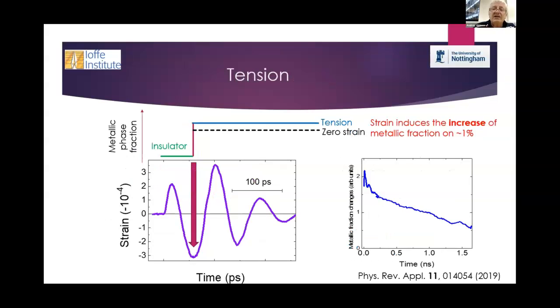So I will show the results first: what happens with tension when we excite the phase transition at the moment when it is the tensile part of the strain pulse. The upper curve is just the scheme, and here we have the experiment. What we observe is that the amount of material which has undergone phase transition increases, relative to the case of zero strain. If we monitor this in time, we see that this increase decays in about 1 nanosecond—much smaller than the lifetime of the metastable state. So we have this increase here, and you will see the graph of what we measured in compression.